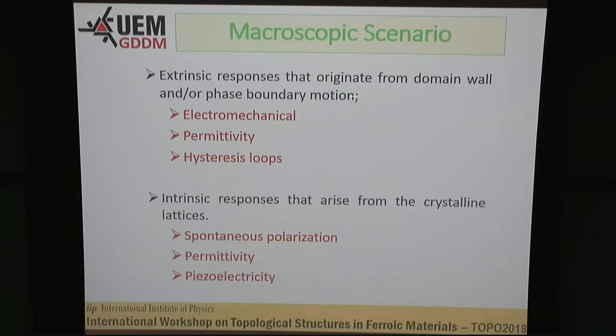And of this extrinsic response, we have some that originates from the domain wall, like electromechanical response, permittivity, hysteresis loops, that is very linked to the domain wall movement, and the intrinsic response that arises from the lattice: spontaneous polarization, permittivity, piezoelectric response.